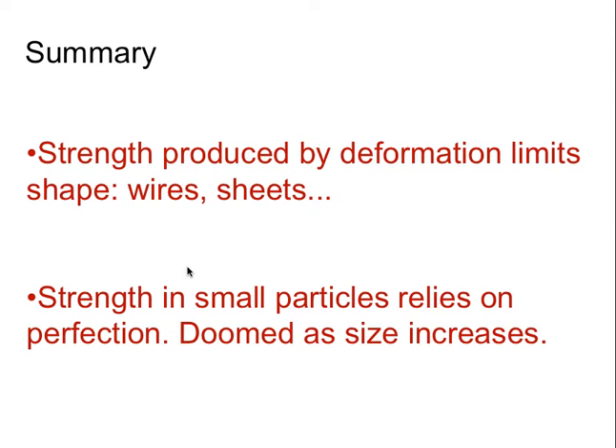To summarize: strength produced by deformation is limited in shape. If you rely on perfection, it's doomed as size increases. This won't be the method to produce bulk nanostructured material which is strong.